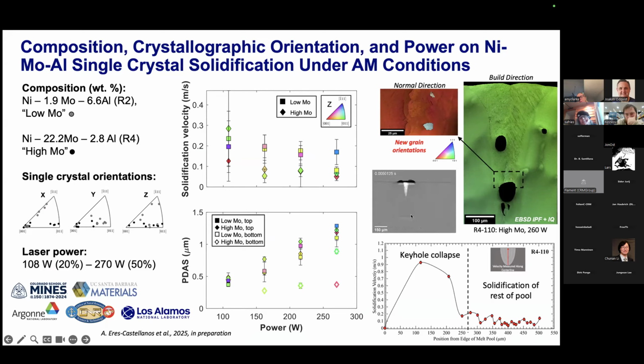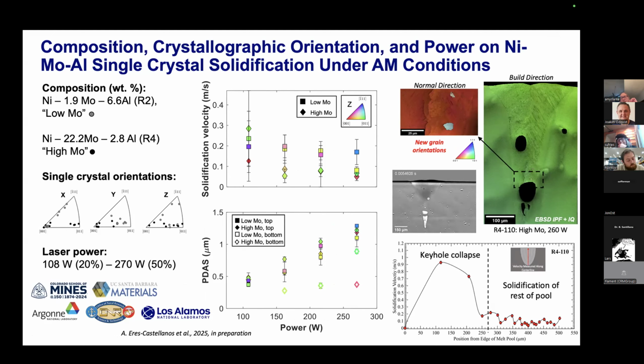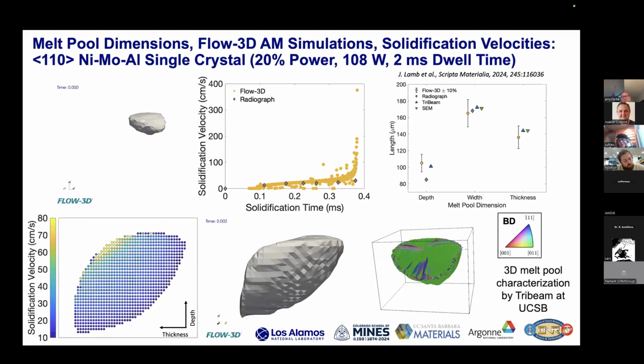When we go to higher powers, we tend to have more chaotic melt pools and often have keyholing and keyhole collapse that happens. So this is an example of a high power condition where we have a keyhole collapse, where we have a spike in velocity, and then it's sort of business as usual for the rest of the melt pool solidification. And if we go in and we look locally at that keyhole collapse region, we actually see some new grain orientations. So we have a velocity that's high enough to trigger columnar to equiax transition and sort of those much finer kinds of microstructures as well. And we tend to see that at higher power conditions, which does make sense. So the GV construct allows us to understand microstructure, but also the formation of defects as well.